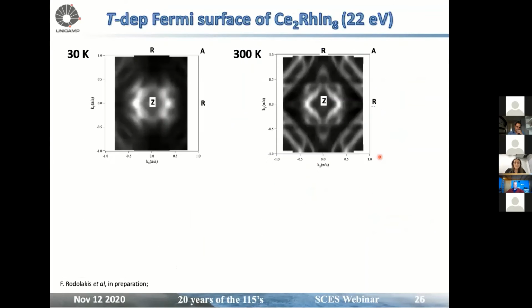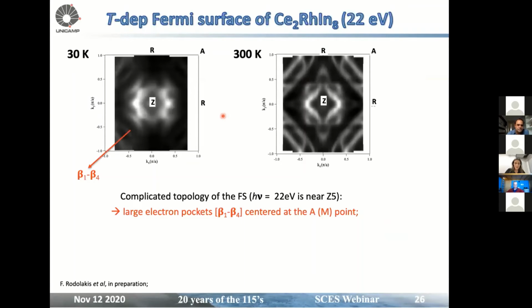So finally, the reconstructed Fermi surface of Ce2RhIn8 at low temperature, high temperature, yay. So things are changing, but not too much. We see complicated topology of the Fermi surface. At that energy, we are near the Z point, so that is even worse, it changed less.